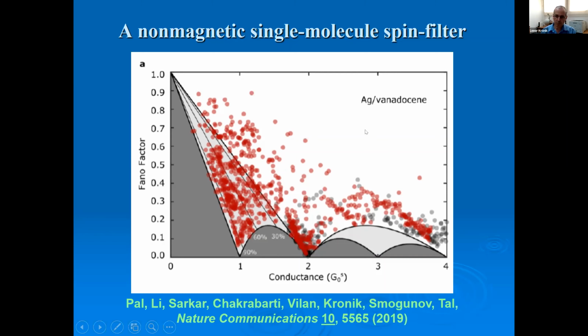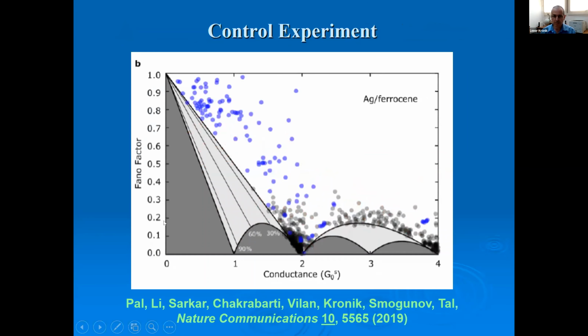So then we superimpose this with the actual experimental data, which are the various red dots. And we see that, first of all, none of them fall in the forbidden area, which means that the theory is reasonable. And that many of them do fall in the region where you have spin polarization, even as much as complete spin polarization, 100%. And as a control experiment, we did the same with ferrocene, which is very similar, except it doesn't have a net spin. And then indeed, within experimental accuracy, not a single data point is within the spin polarized region.